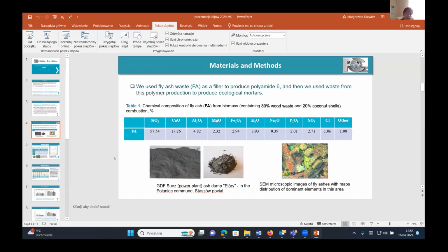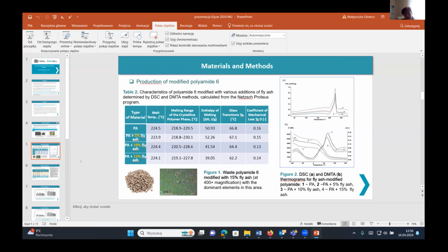You can see in the table the chemical composition of fly ash from the company in Połaniec, Poland. This is the biggest energy company in Poland, combusting wood waste and coconut shells. This is 18 to 20%. Can you see the microscopic image? This is homogeneous waste. We first use it for the production of modified polyamide 6, with 5, 10, and 15%.